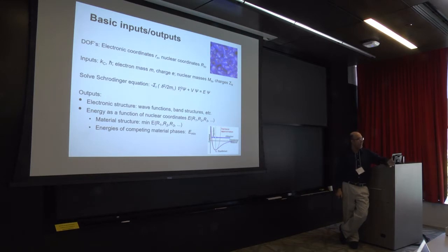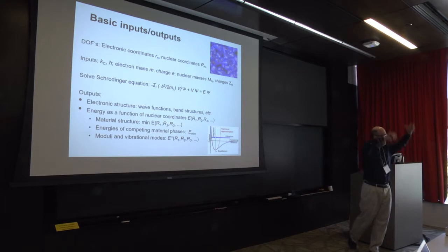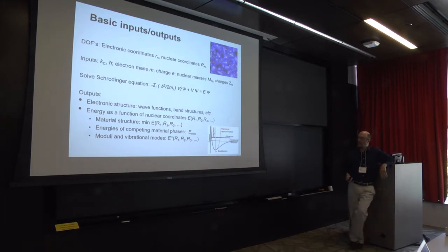I can compare that from one phase to another. I can build up phase diagrams of different combinations of materials, all of that kind of information. I can also look at the curvatures involved here. Those are going to tell me the spring constant of the molecule, the elastic moduli that I need in these continuum simulations of my crystal. They also tell me all about the vibrational properties, and we'll look at those in a moment.